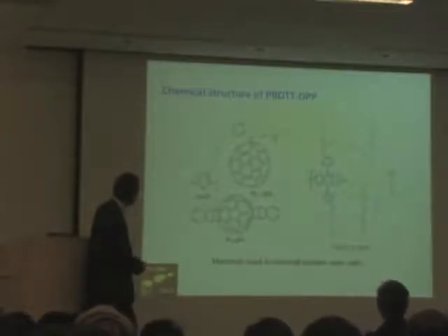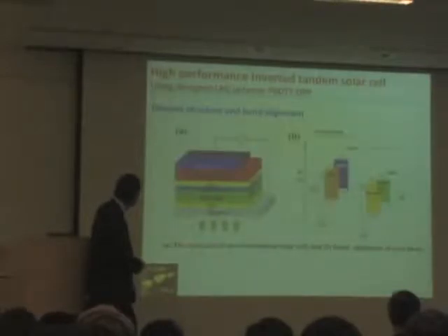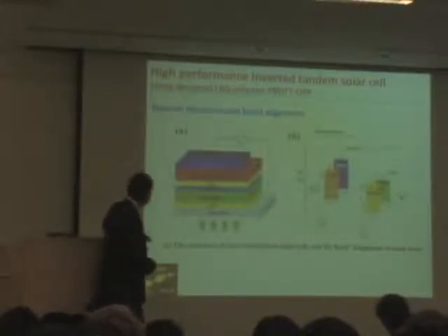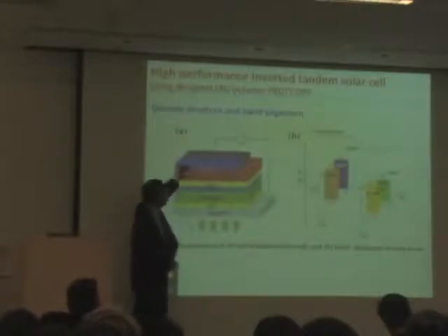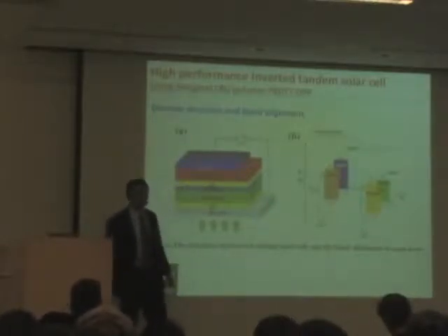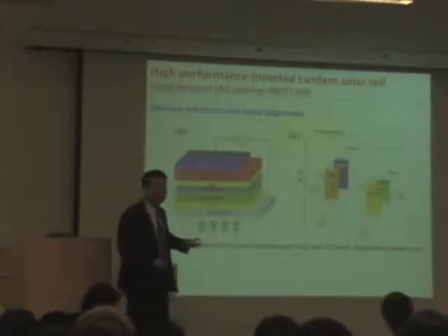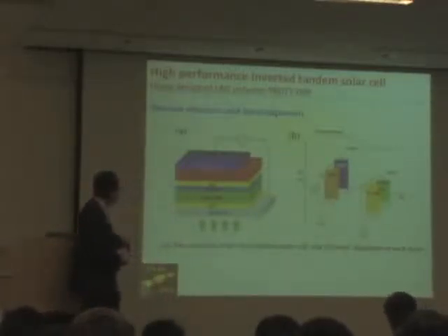So let's go back to the cell structure. We have ITO glass and solution-processed zinc oxide. P3HT:ICBA is the front cell. PEDOT:PSS, we still use PEDOT, we just have to live with it for a while. And solution-processed zinc oxide. And the low bandgap polymer is the material I just described, PBDTT-DPP. And then moly oxide and the silver. So everything from here to the top is solution processed, except the silver electrode. We still have to do thermal evaporation. From the manufacturer's point of view, if one can do all solution processing, that would be tremendous and simplify the process. Okay, so I have to speed up a little bit.